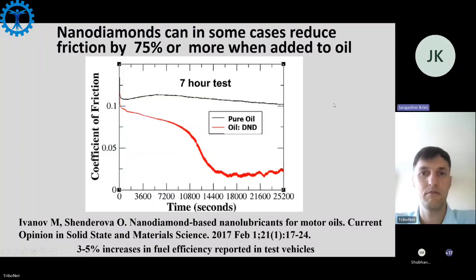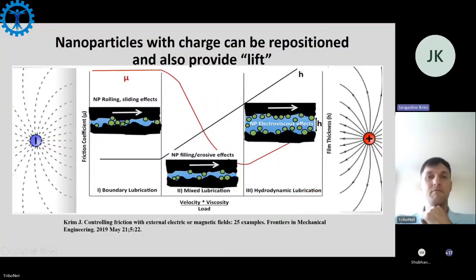They have, in some cases, just had a dramatic effect on friction. Here's a coefficient of friction. Now we know pure oil is not a good lubricant, but nonetheless, adding nanodiamonds to oil is reported in these conditions to drop the friction coefficient dramatically. This same group put the nanoparticles in their test vehicles. And you can buy them now and put it in your car if you want. They say a 3 to 5% increase in fuel efficiency. All right, well, that's the company selling it. So let's move on. Let's go to the next slide. Some of the good things that can be repositioned.